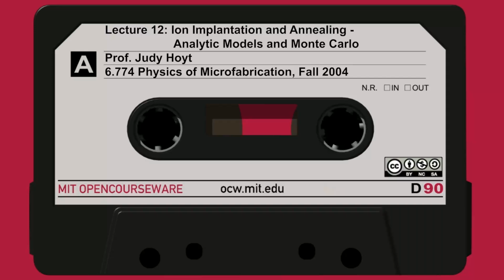So on the left-hand side, I'm just showing a schematic, just reminding you from the first lecture what people do for a VT adjust implant. For example, if you're making an NMOSFET on the right-hand side, you would ion implant with boron a very, very thin surface region. You block off with photoresist the PMOS area, and you would implant boron to adjust the threshold voltage.